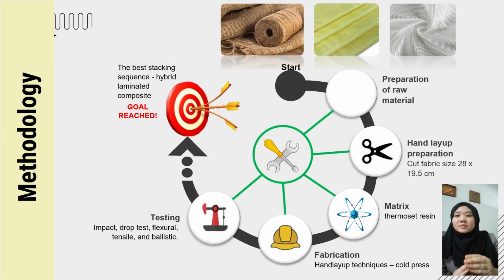Here is the methodology. At first we start with the preparation of raw materials, which we are going to use: the epoxy, jute fabric, Kevlar and fiberglass fabric. For the hand layout preparation, we will cut the fabric into a size of 28 times 19.5 centimeter, and then we use the matrix, which is the epoxy resin, and then we fabricate the composite using the hand layout technique with cold press, and then we test the specimen with impact, drop test, flexural, tensile and ballistic. Then lastly we get the best stacking sequence, hybrid laminated composite.